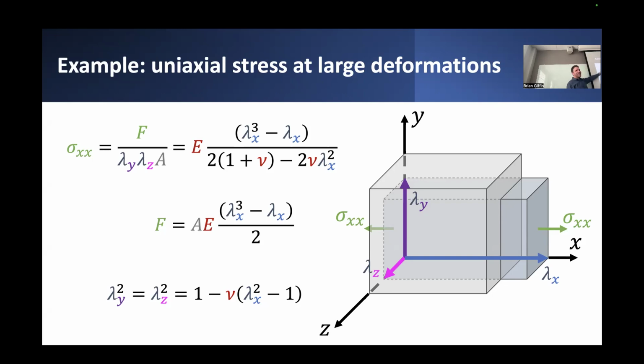We can also figure out different expressions for different measures of stress, like the Cauchy stress or the true stress that would be applied over this front face of the cube. And really all that it requires is, again, if we have this expression for force, we can plug it into our expression for Cauchy stress, which is really just the initial area scaled by these different edge scaling ratios, where the lambdas in the y and z direction should be less than 1, indicating that this overall area is actually shrinking. And if they're less than 1, what this basically means is that F divided by A, now divided by some quantity that's less than 1, implies that sigma xx is going to be greater than F divided by A alone. So as the cross-sectional area starts to shrink, the Cauchy stress is actually going to appear to increase, inversely proportional to the rate of decrease of the cross-sectional area under deformation.